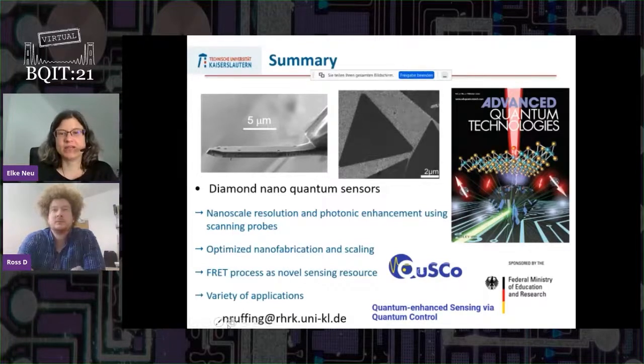So typically, if we just look at this shift of the resonances, we get a microtesla per square root of hertz. So it means within 1 second you can measure a change for a static field of a microtesla. If we have oscillating fields and we can do this coherence-based sensing or AC sensing, we go down to nanotesla. So this is what we can do at the moment.